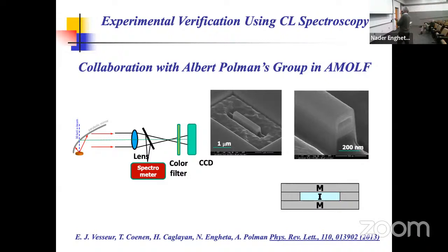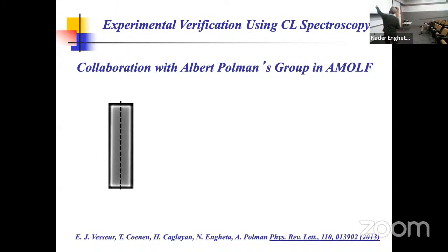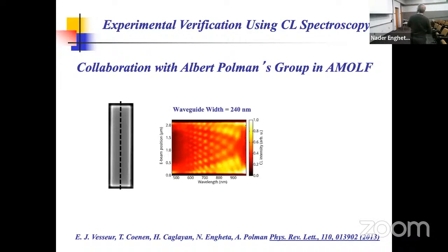When you put this sample on the stage that you see over here, you can move that stage, and at every point that the electron beam hits, you can record the photons that you get. So we could have a map of photon radiation as a function of the position of the electron beam, with a resolution of 4 nanometers. Let me show you what we did. This is one of those waveguides, and this is the top view of that, with the electron beam coming normally to this. At every point that the electron beam hits, we record the photons, and we plot the intensity of received energy as a function of wavelength. This is what you get. The vertical axis is the location of the electron beam hitting the waveguide from the top.